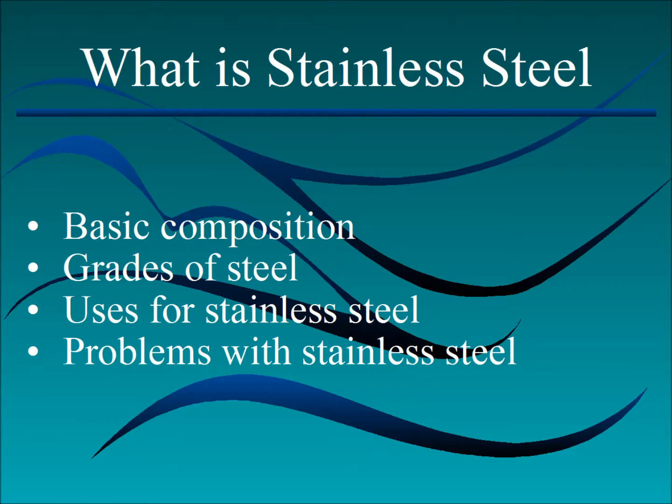These are the martensitic and the ferritic, with no nickel, lower amount of chromium, and what the trade-off there is, these are hardenable alloys, so that you can get the hardness that you can't get with the austenitics. So you're losing a bit of corrosion resistance, but you're getting the hardness that is required to maintain the blade for whatever purpose it's being used for, surgery or something else.